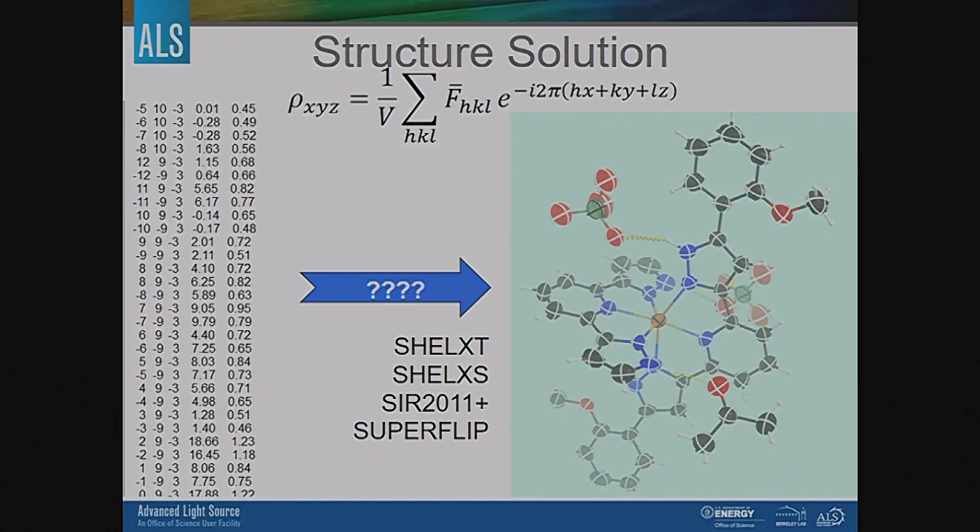Well, most structure solution programs use a combination of different methods. They use phase relationships. So we have things called negative quartets, where we have reflections whose phases are related because of their Miller indices. And we also use statistical methods. So in essence, as far as the time we've got in this talk, you're going to trust me, it's a black box, and we do statistical methods, and we get phase sets that produce realistic electron densities.